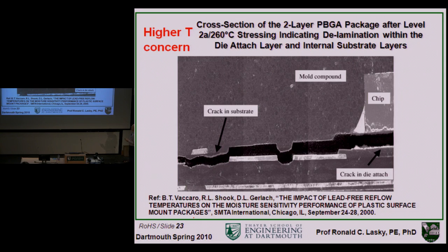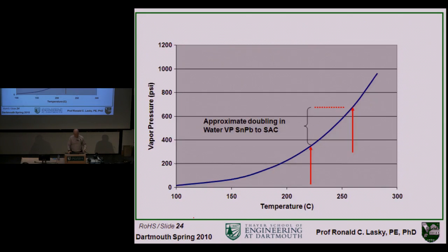And actually at some of the interfaces, if it's been exposed at a high humidity and gone through some temperature excursions like hot to cold, you can actually get potentially a little almost physical water precipitating in an interface like this. The temperatures of lead-free soldering are high enough that when they go through the reflow oven that melts the solder, you can literally have an explosion of steam, and it can actually blow the package apart like this one's been blown apart. And one of the reasons to see this is the vapor pressure of water is not linear with temperature.